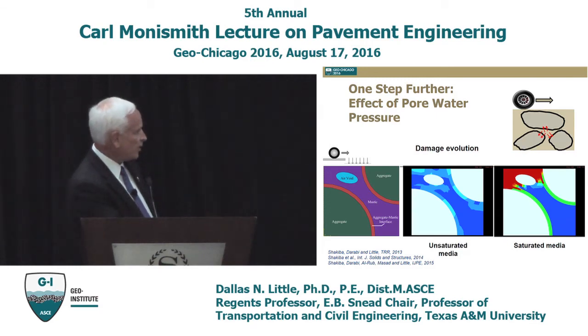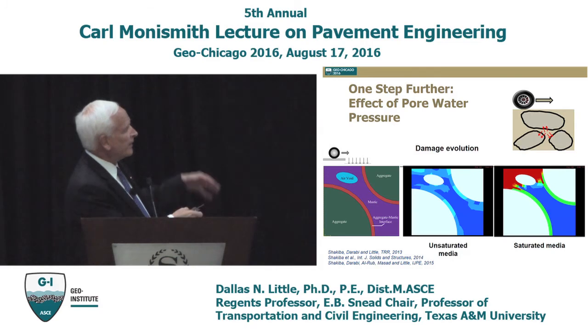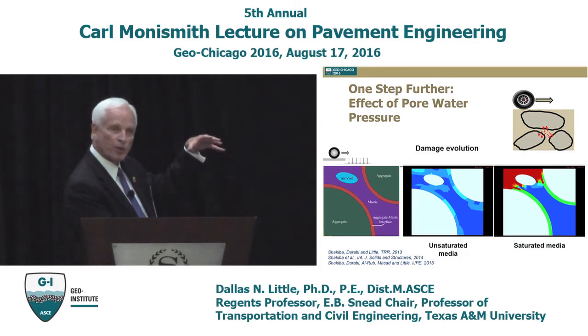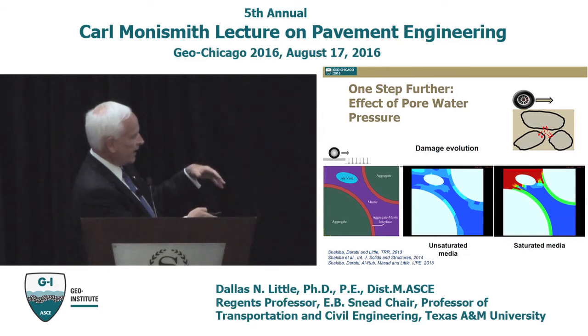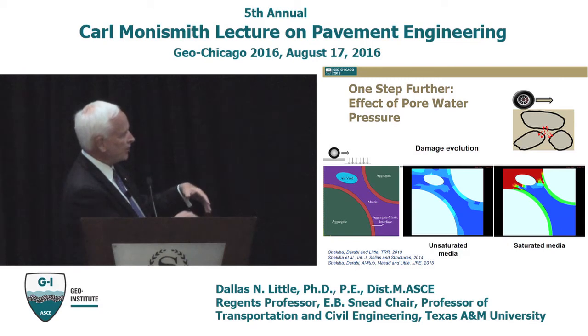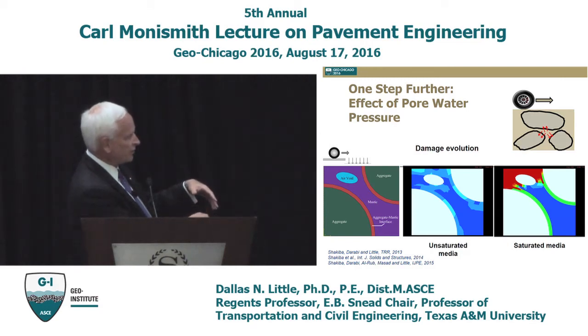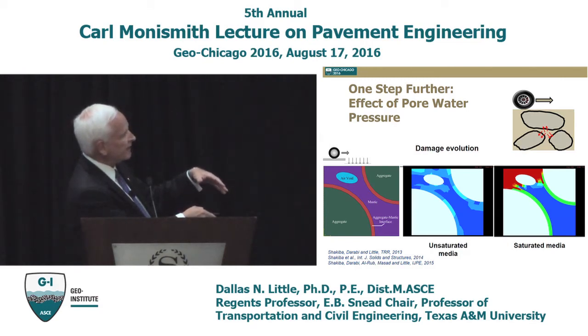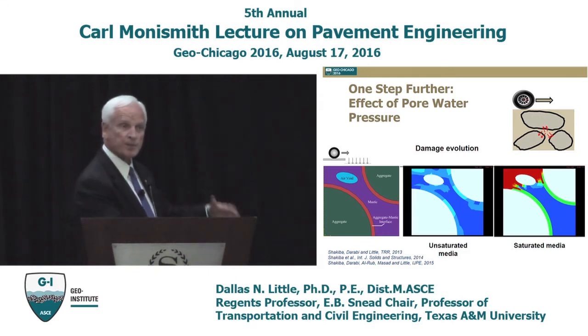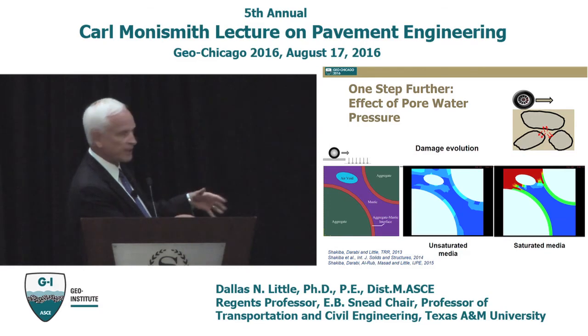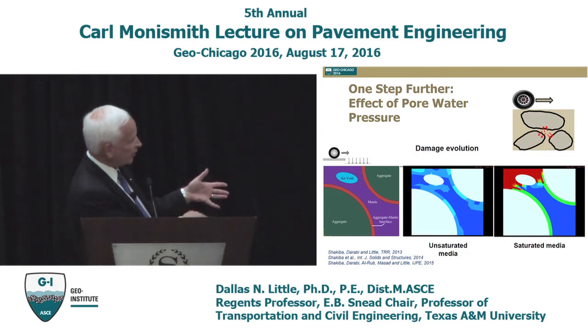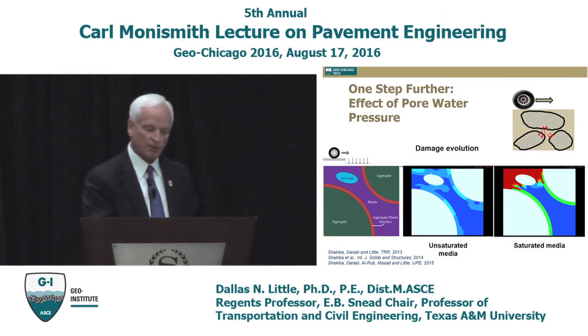If we apply a load to this material, then the mechanical process coupled with the moisture diffusion allows us to envision the rate of damage. And you can see that when it's a saturated media, that rate of damage is going to be a whole lot faster, because the hot colors represent a higher level of damage, the cooler, lighter colors, a lower level. When it's unsaturated, of course, the damage process is lower.